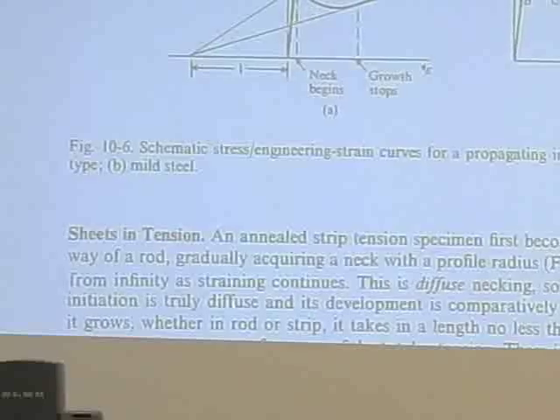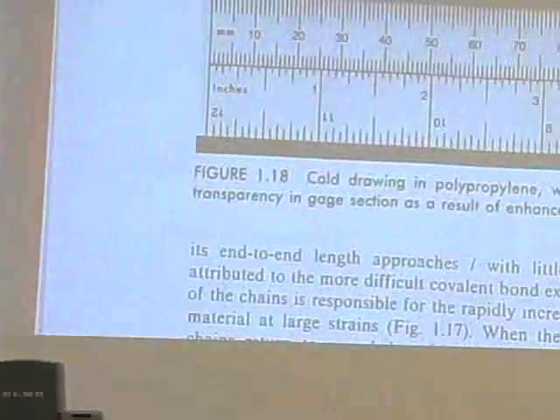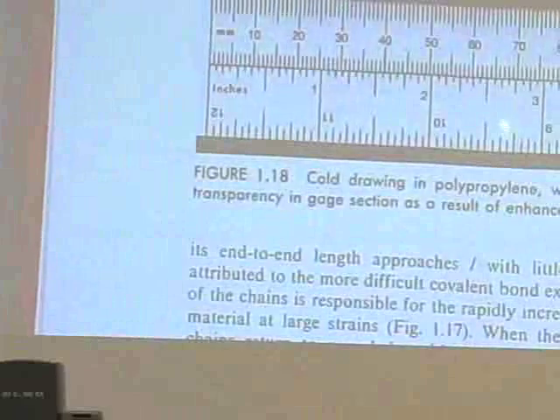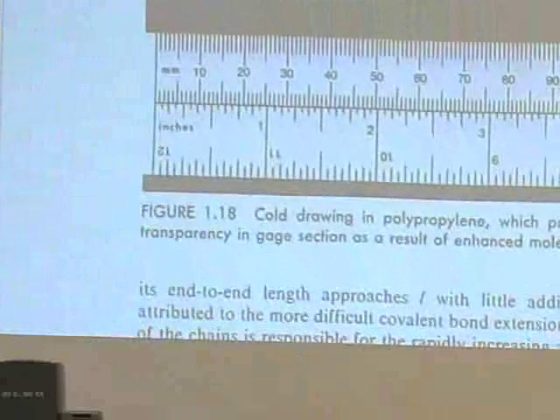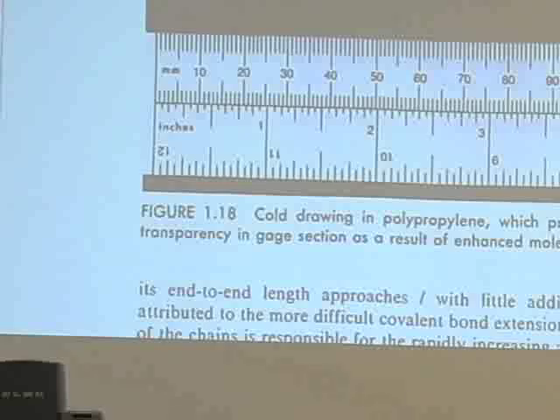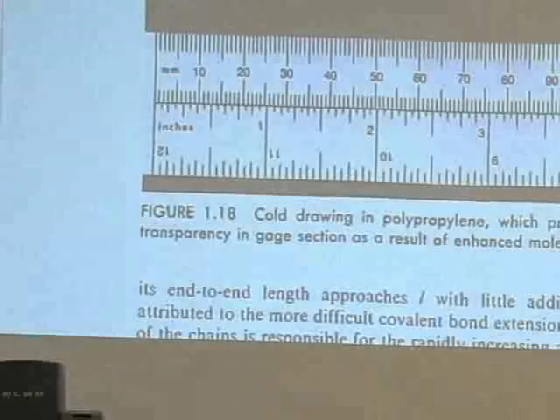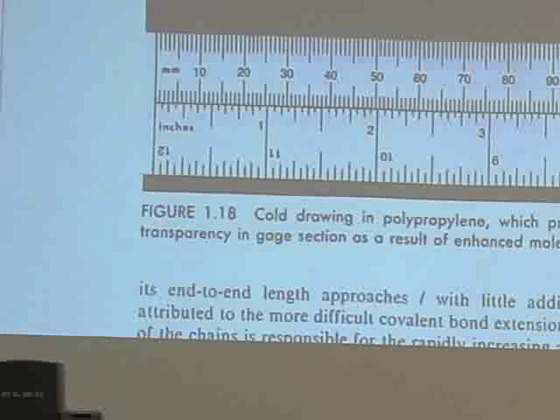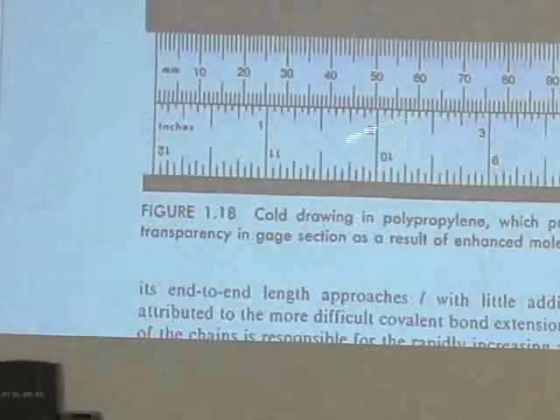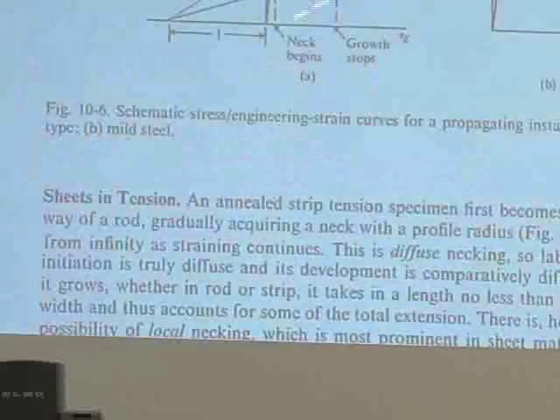And in a polymer, it actually looks like this. I think this is out of Hertzberg. That might be in your text. Cold drawing in polypropylene. Polyethylene and polypropylene both behave basically the same. If you took a tensile bar like this and started pulling on it, you would see one region, the thin down region, start to neck down as soon as you get yielding. As you keep pulling, nothing else deforms, but that band just grows until it consumes the whole thing in both directions. And when it consumes the whole length, that's when the whole thing starts to go up again.